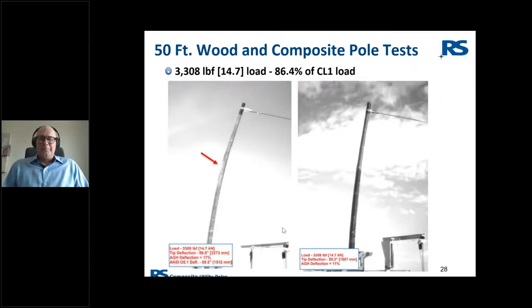Now the next one is not 100% of load. It is 86.4% of class one load, and this is where this pole started to break. Just for reference, this Western Red Cedar class one pole is test two of the poles, which is sort of in the middle cluster, if you will, of the wood poles that were sampled in that sample set of five. The tip deflection here is about 90 inches, exactly 50% more than the predicted ANSI value of 60 inches. And that represents an above ground height percentage of 17. Over on the right, the RS composite pole, tip deflection is 59 inches, so right in line again with the ANSI predicted values, and that's 11% of its above ground height.